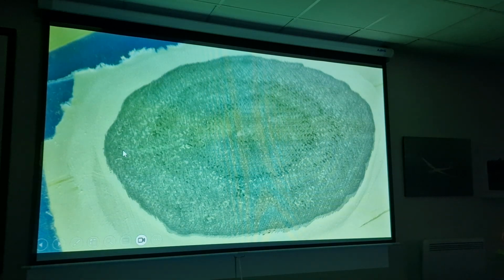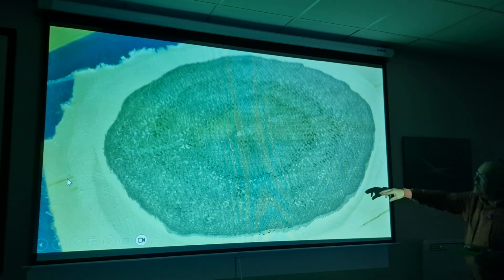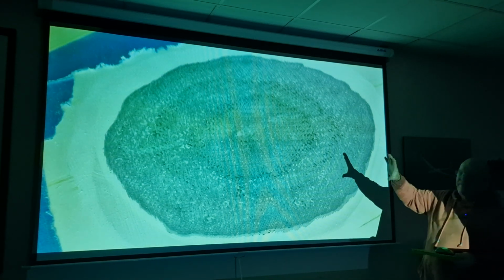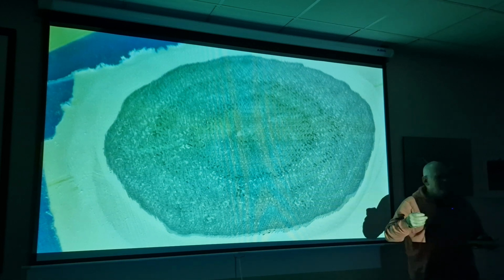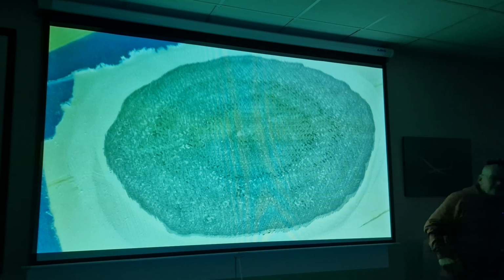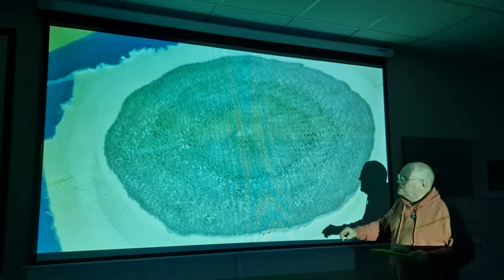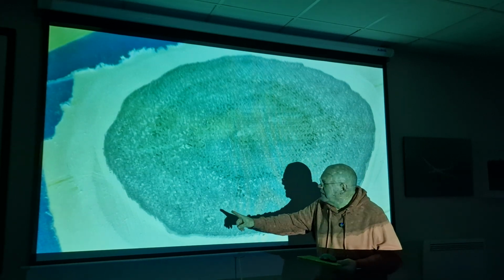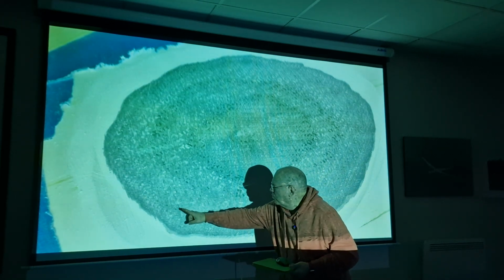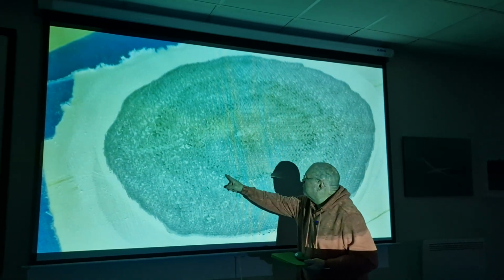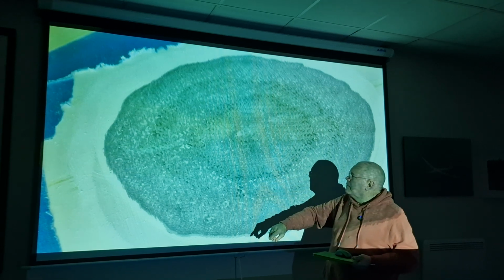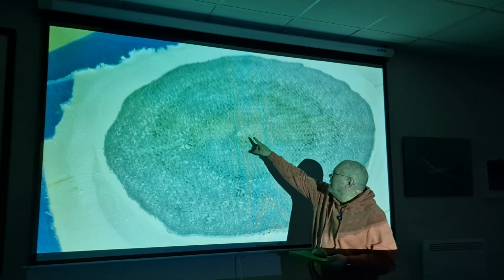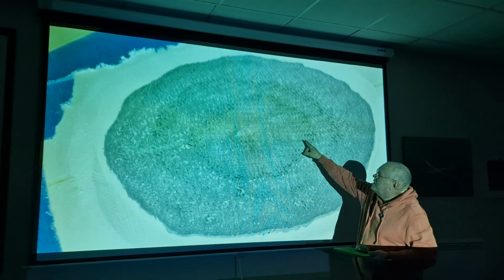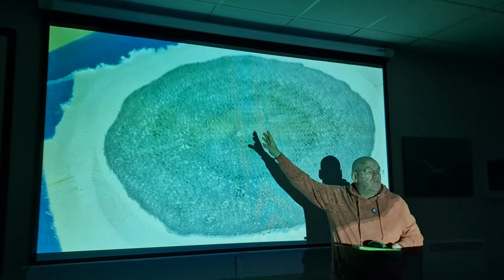This, I think, is a work of art. This is a Discus belly, and the Discus belly has a really thick type of glass fibre. Imagine a really thick 3mm of plywood. This is what a Discus belly is. It's quite thick, with layers of glass fibre, and each one of these layers, there's four: 1, 2, 3, 4. And what you can see here, there's a small white patch in the middle. That's because there's a frame inside that's broken.